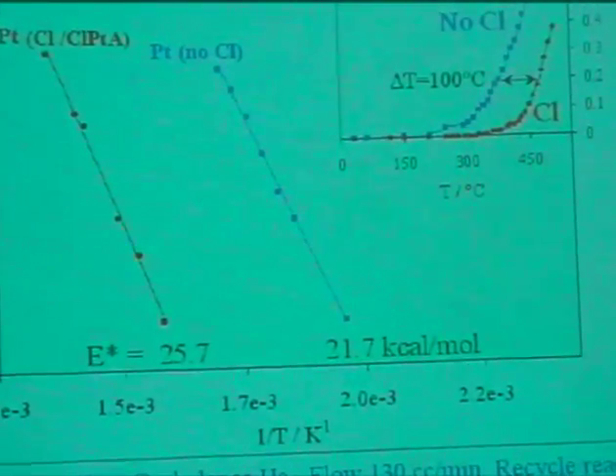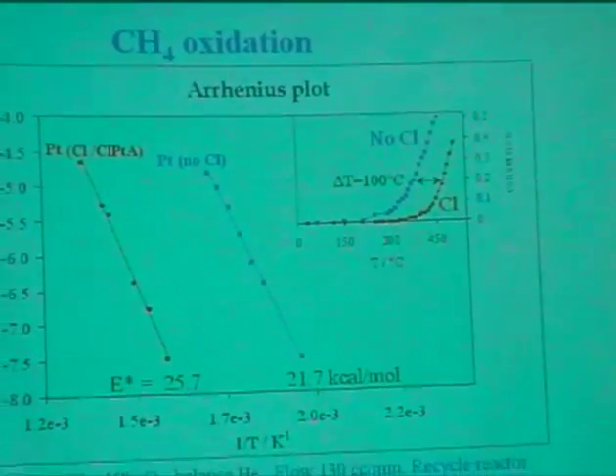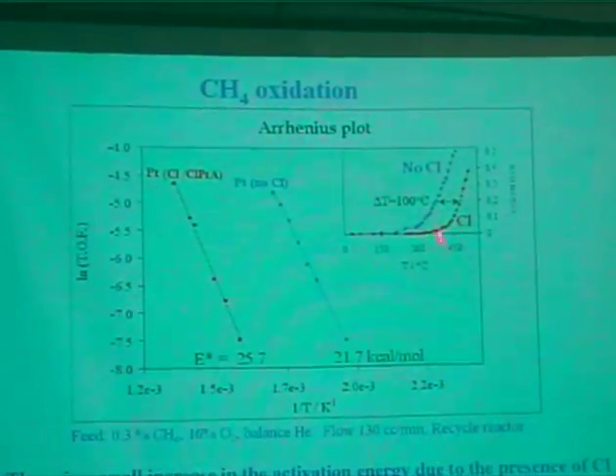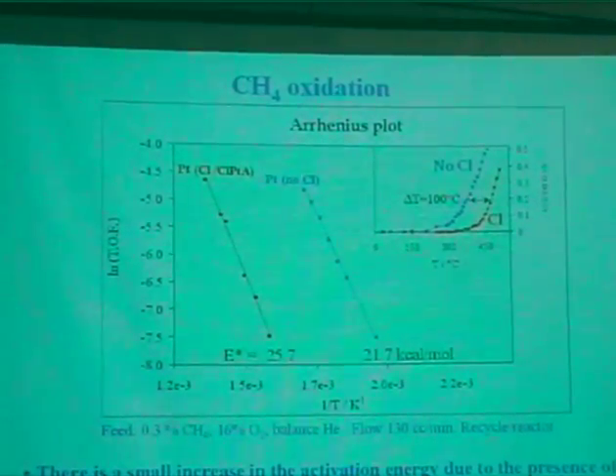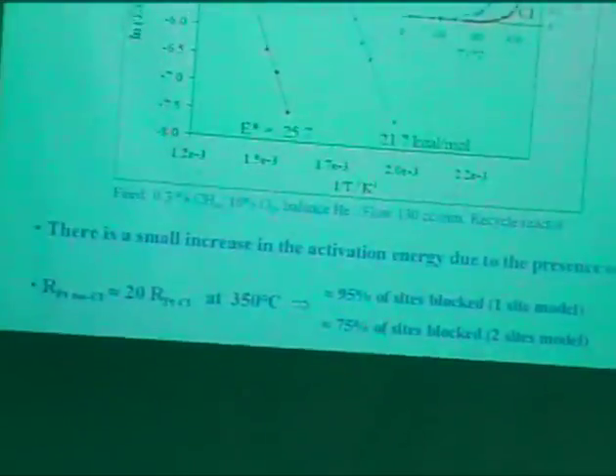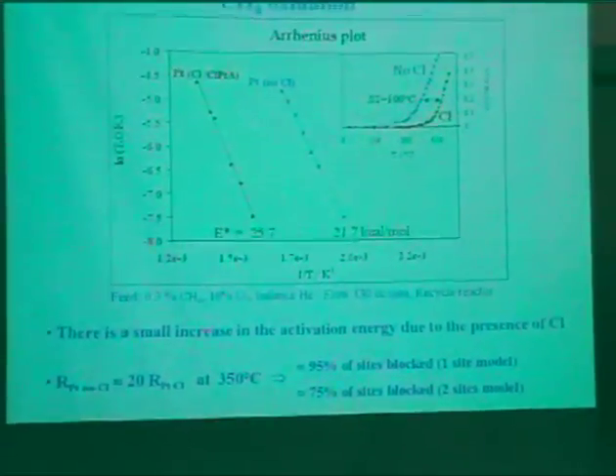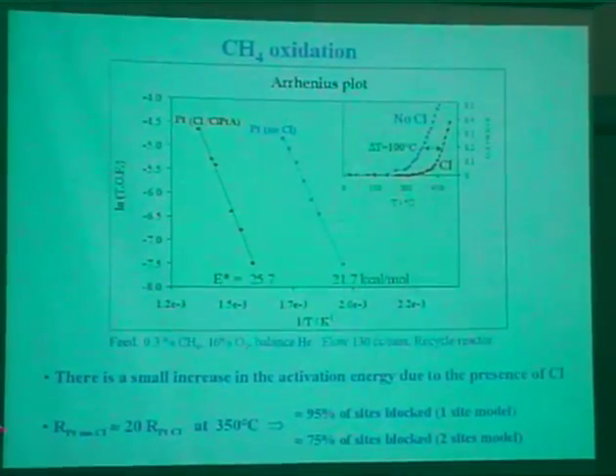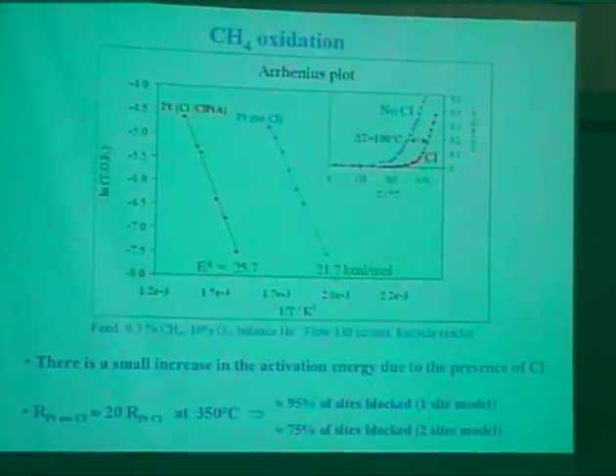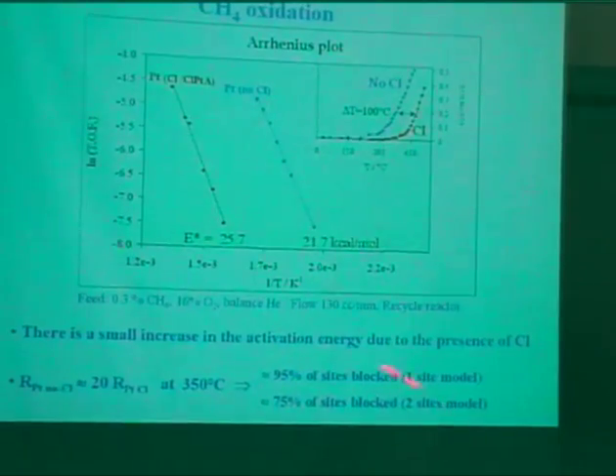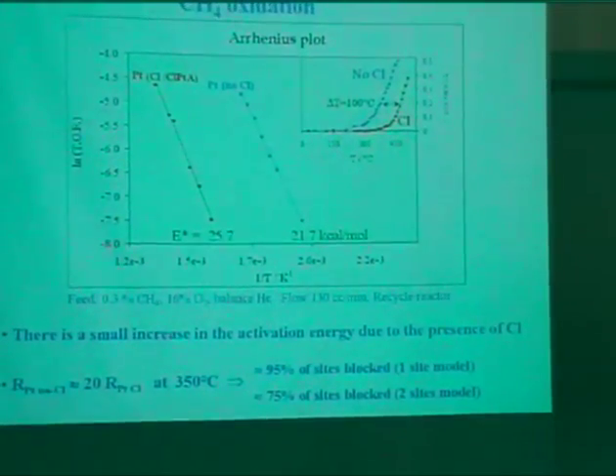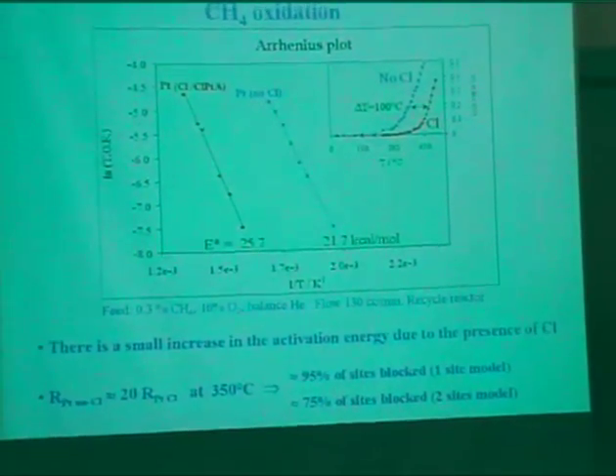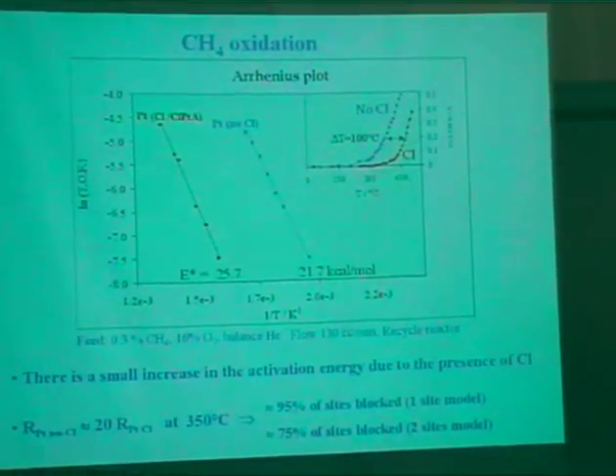But the important thing is that here we have these activation energies, and very little reaction at 350. There is a very significant difference in rate, about 20-fold, between the rate with chlorine and without chlorine. If we do a calculation under this condition, of course the sites are being opened up, but under those conditions where we do this comparison, 95% or so of the sites are blocked by chlorine, so that you get that low rate. If you have a one-site model, about 75 or 70% if you have a two-site model.